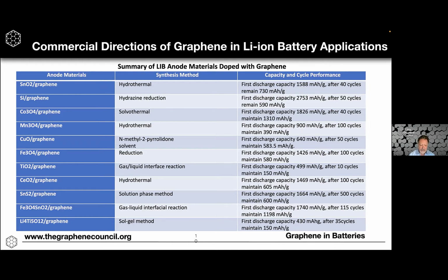If you look at the cobalt oxide graphene, it maintains the highest capacity over numerous cycles. But if we go down to the iron down here, this has 115 cycles and maintains nearly 1200 milliamp hours per gram. So there are different options. You don't necessarily have to tie yourself to graphene, and silicon is the sort of message to be drawn here.